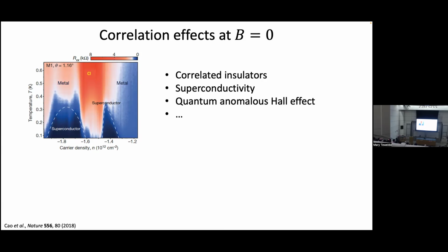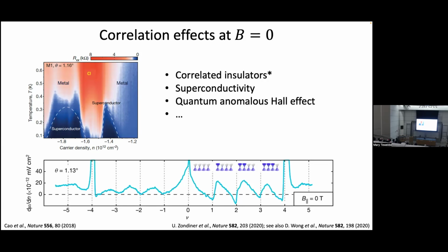Okay, so here's magic angle twisted bilayer graphene, this picture that I showed you before. I said there's a correlated insulator at half filling. Actually, if you measure in the way that we did previously with a single electron transistor, you don't find a correlated insulator at half filling. So you should get a peak here, right at nu equals 2, if this thing were truly thermodynamically gapped. And oftentimes it's not. So sometimes you see that, but oftentimes you don't.